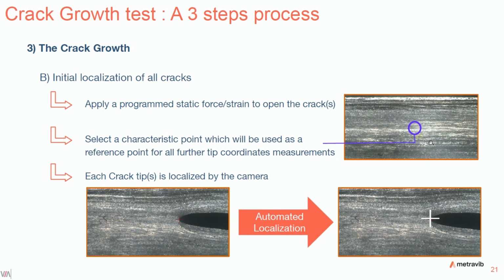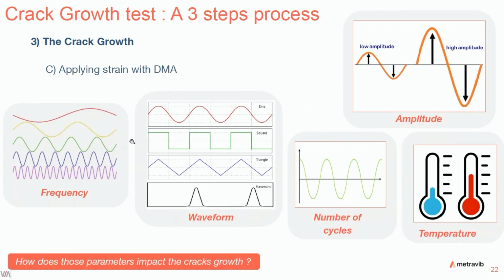So the camera localizes all cracks. We apply a static force or strain to open the cracks. We select a characteristic point, which will be used as a reference point, and each crack tip is located by the camera. You have an example in the picture below on the slide. We apply strain with the DMA, that is to say, we can control the frequency, the waveform, the amplitude, the number of cycles, and of course, the temperature.